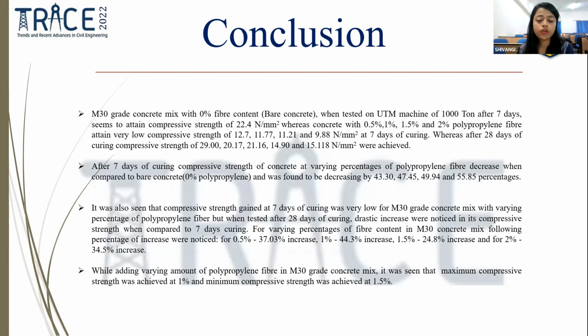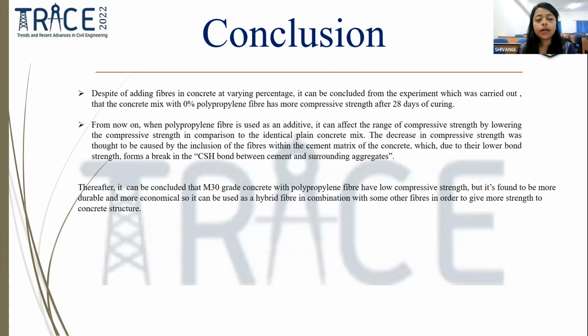While adding varying amounts of polypropylene fiber in M30 grade concrete mix, it was seen that maximum compressive strength was achieved at 1%, that is, when we added 1% polypropylene in the M30 grade concrete mix. And minimum compressive strength was achieved when we added 1.5% of polypropylene fiber. Despite adding fibers in concrete at varying percentages, it can be concluded from the experiment that the concrete mixed with 0% polypropylene fiber has more compressive strength after 28 days of curing.